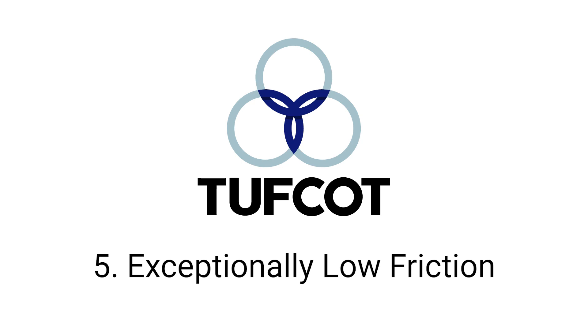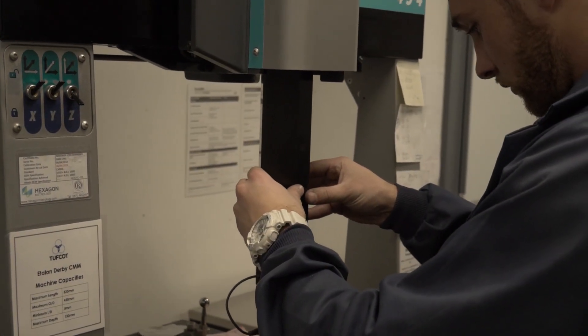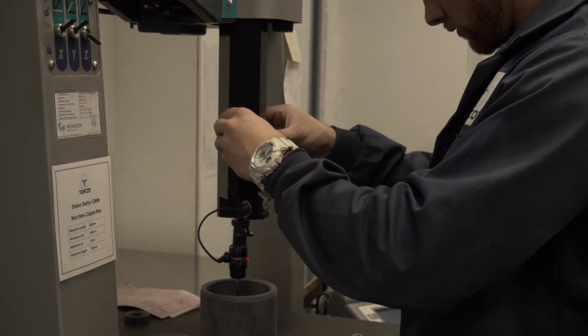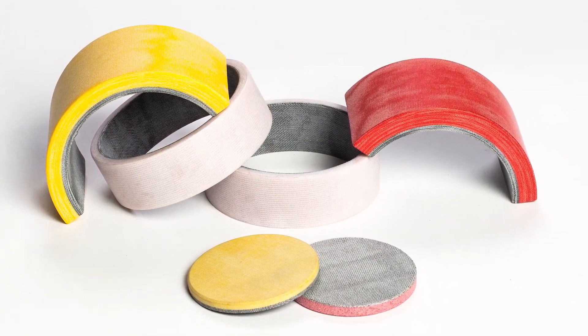Tufcot has exceptionally low friction. In recent testing, our Tufcot 200MP material recorded a dynamic coefficient of friction of 0.15, making it ideal for standard bearing applications where low friction is required. Lower values can be achieved with other grades, namely our XPL range, which incorporates a PTFE fabric onto the wear surface of the parts.